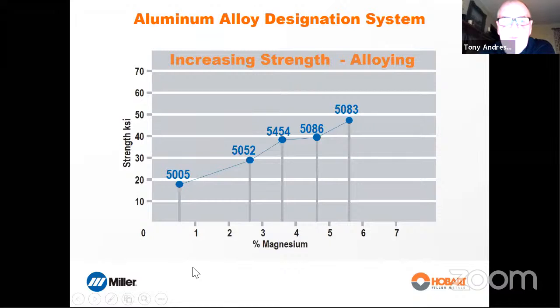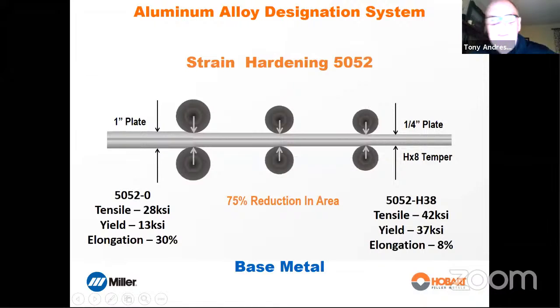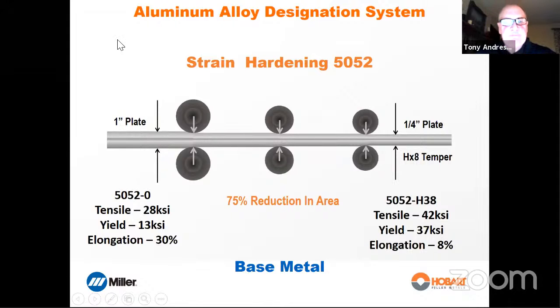This is a non-heat treatable alloy. It will not respond to heat treatment in terms of strengthening. If we heat it to a high temperature, we will anneal it, we'll drop it to its lowest strength. But other than that, we cannot increase its strength by thermal treatment, just strain hardening, okay? So what is strain hardening? We take a 5000 series or any of the non-heat treatable alloys, or even the heat treatable alloys for that matter. We can strain harden them all. They all will respond to strain hardening.